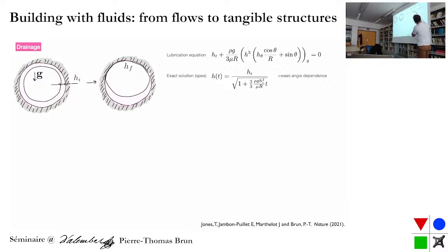But what you see is that if time is large enough, essentially you can neglect the 1 in your square root here. And so if you cross the 1, you can take the hi square outside of the square root and you can cross it with this hi here. So the thickness no longer depends on the initial condition. So you go to something that is sort of universal. This is for Newtonian fluid.